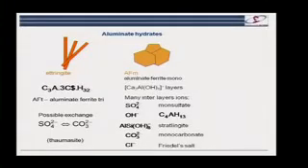For the purposes of hydration, the 2 most important ones, or perhaps the 3 most important ones, are this phase we call monosulfate. This is where we have instead of having 3 sulfates, we have 1 sulfate. The hydroxide AFm, which is also called C4AH13, and also the monocarbonate is important because this is how the small amounts of limestone can react. They can react to give carbonate ions, which go in these AFm phases. So because there genuinely is so much variation in these AFm phases, we tend to use loosely the word AFm just to talk about them collectively.